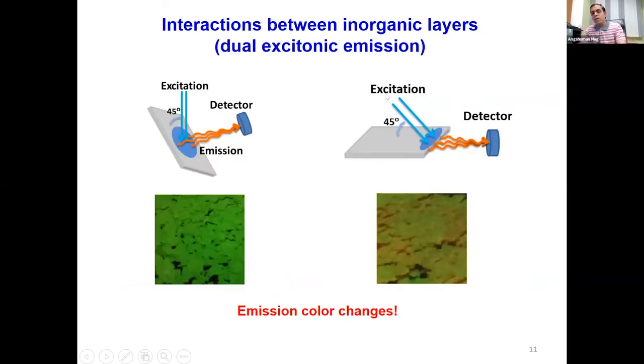So far, whatever we have discussed is mainly about the properties that come from the interaction between the inorganic and organic layers. However, there is also a possibility of an interaction between two adjacent inorganic layers. We got motivated to work in this direction based on some experimental observations. For example, these are the colors of the luminescence coming out from crystals of layered perovskite, and we see that under different measurement conditions there is a change in the colors.